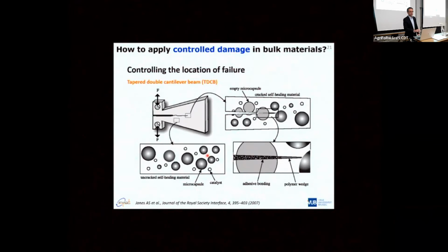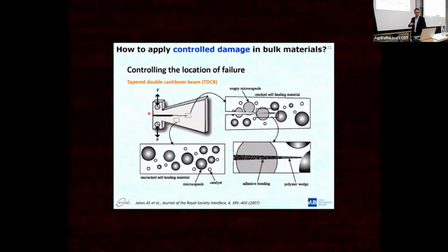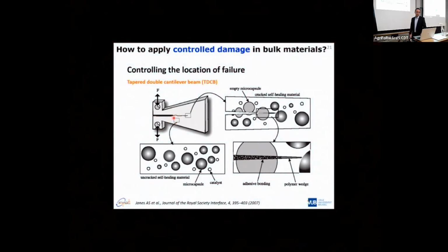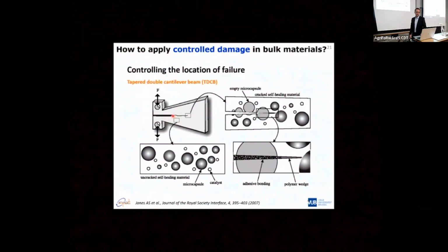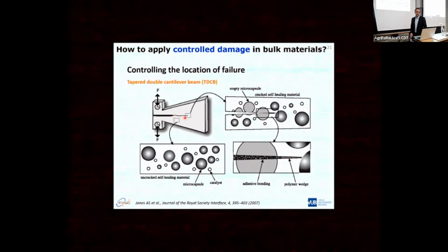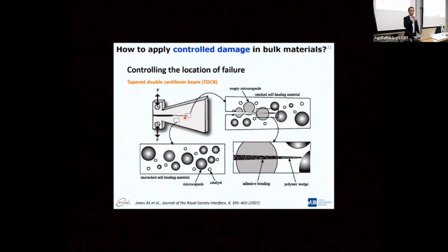For thermosets, things like the tapered double cantilever beam were developed, where through the design, you make sure that you have the stresses located here where you have a small cut into the material. Your crack tip will actually start here and then grow into the material as you do a tensile test. So this was developed for thermosets, and to study then self-healing.